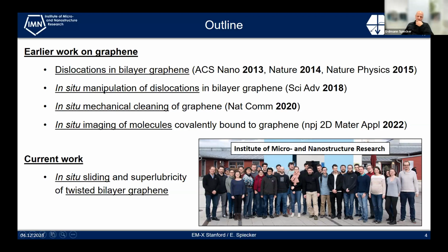Later on, we achieved in situ manipulation of dislocations, so we could manipulate individual dislocations by in situ microscopy in the TEM and SEM. And later on in this context, we also developed a cleaning mechanism which allowed us to clean graphene to atomic cleanliness by in situ mechanical methods. We used this later on to image individual molecules covalently bound to graphene. I want to show a little bit about this early work.